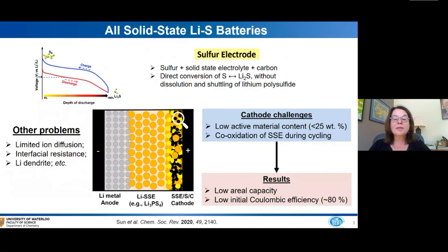What's pretty surprising is that in the solid state, you can actually trigger the conversion from sulfur to Li2S, which is reversible. Of course, the advantage is that this prevents the dissolution and shuttling of lithium polysulfides, which are really problematic in liquid lithium-sulfur cells.